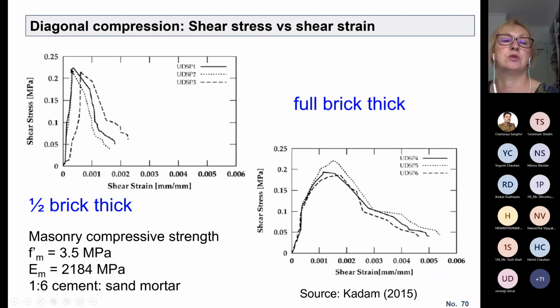So the maximum value, just for your sense, this is for half brick thick specimens and this is for full brick thick specimens. They're on the order of 0.2 to 0.3 megapascals. So it is much smaller. If you recall, we were talking about what is f'm for India, for let's say IIT Gandhinagar.